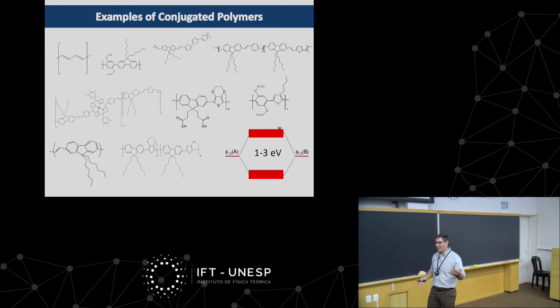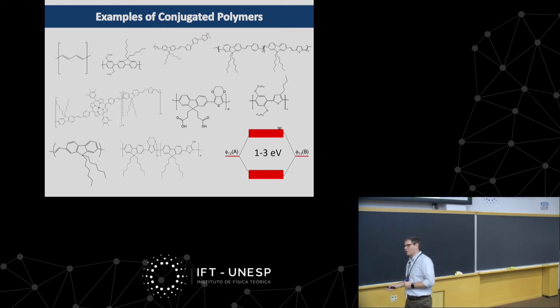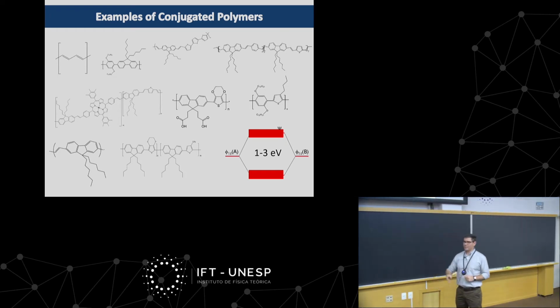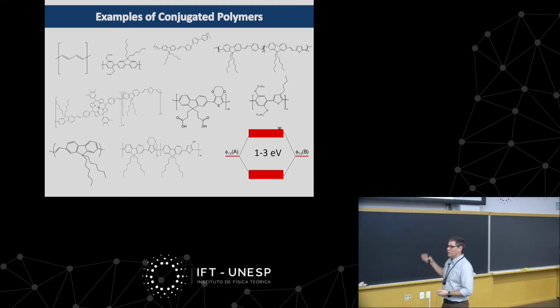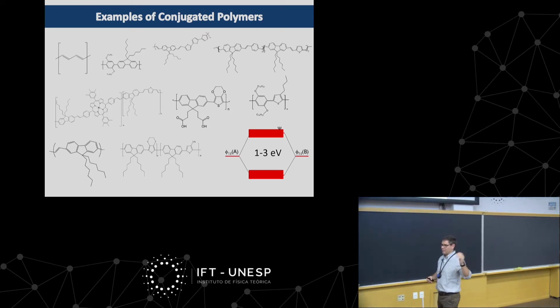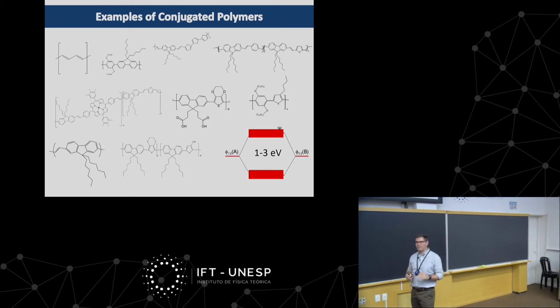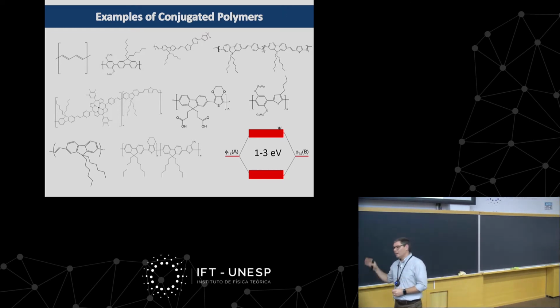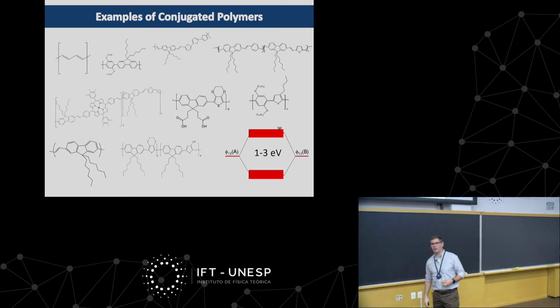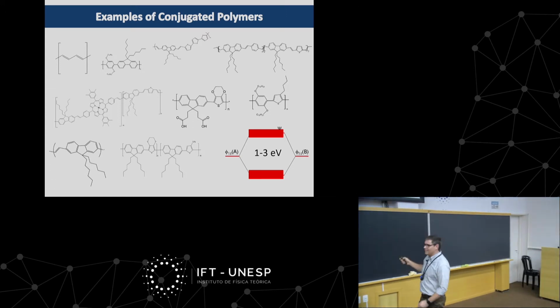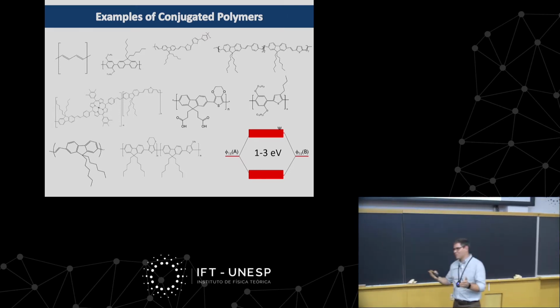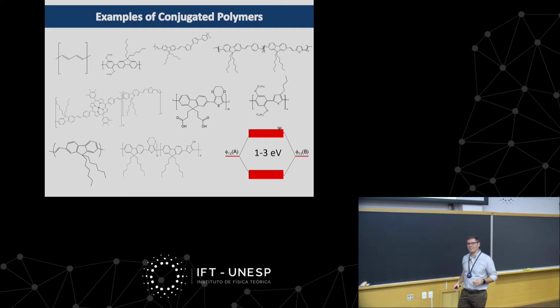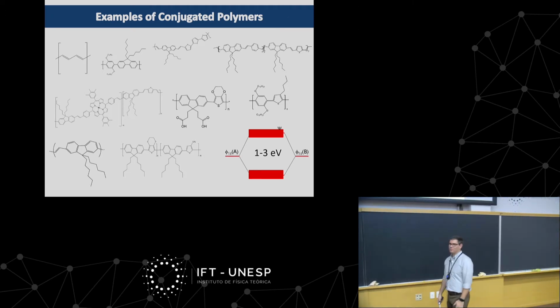What we call HOMO and LUMO, which is highest occupied molecular orbital and lowest unoccupied molecular orbital, which is basically the conduction and valence band. But yes, there is a lot of chemistry and theoretical physicists doing those kinds of calculations. Marília Caldas, for instance, at the USP here, she actually collaborates with us, and she has published recently in Advanced Science, I guess, doing calculations on materials like that used for OPV, which is organic photovoltaics. So it's very important because for organic photovoltaics, you want to have a band gap that actually matches the solar radiation, right? Because otherwise you're going to be absorbing outside of the solar spectrum, and therefore your efficiency will go down. So in order to tell the chemists to make that kind of molecule, you have to do screening calculations, not to lose a lot of time in the lab.